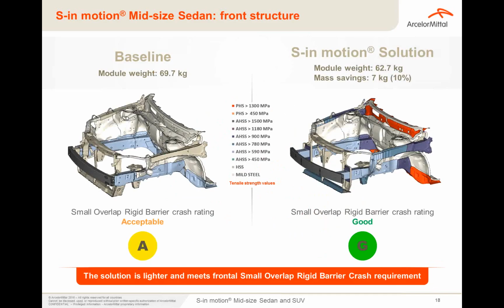Looking at the front structure, we were able to save 7 kilograms on the scope, despite the fact we had to cope with the small overlap rigid barrier crash. So you can see here we saved weight, but we also meet very good requirements, good achievement in this very severe crash test, with a good rating, starting from a baseline with acceptable rating. So that means the solution is lighter and meets the requirements of the most severe crash test currently in automotive engineering.